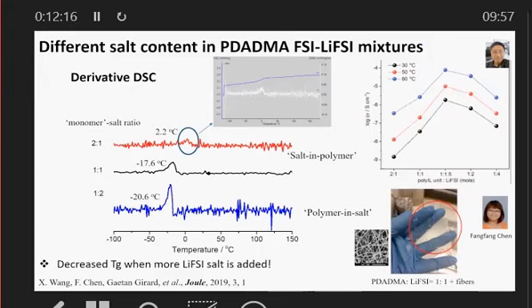So what we see here is we look at the effect of adding different amounts of LiFSI to the polyDADMA FSI system. And we see that here we have the 2 to 1, which is basically 1 mole of monomer to half a mole of LiFSI, and that Tg is 2.2. Then as we add, whoops, so that is what happened there.